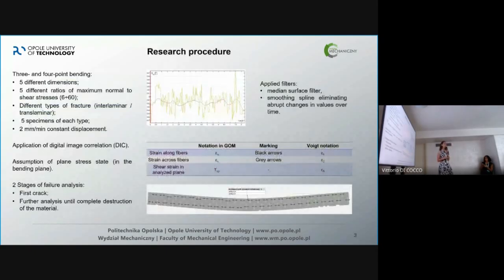During my research procedure, we analyzed 5 different types of dimensions. I will show them later, which gave us different ratios of maximum to normal stress and strain during bending. Like we have bending in our material. And thanks to this, we have different types of cracks, either translaminar or interlaminar. Both of them are very dangerous, especially in composite materials, as the first is growing, and then suddenly we have a crack without saying, hello, I'm going to crack. It's just cracks, and we can have very catastrophic results.